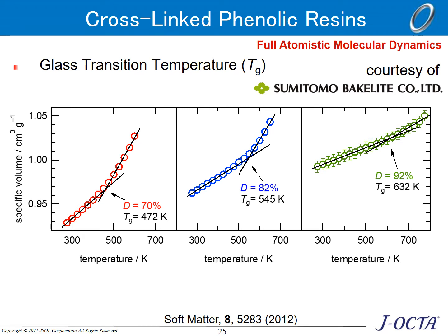On the other hand, it should be noted that the glass transition temperature is higher than in the experiment, because of the fast cooling process. Molecular simulations show how the degree of cross-linking, or the molecular structure, affect the physical properties of the material.